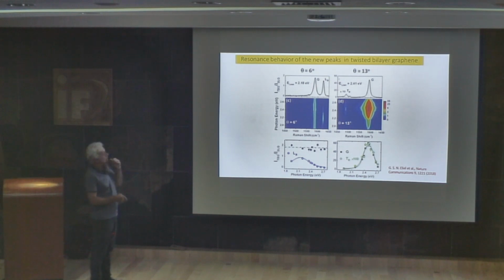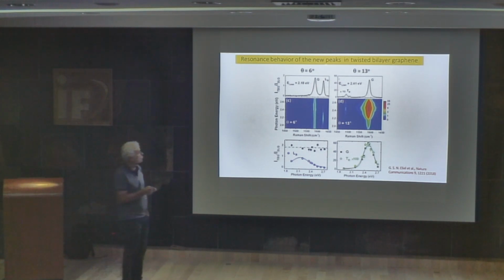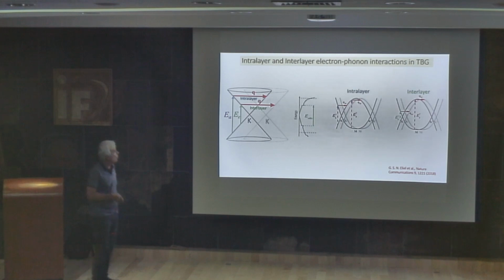Okay, then I don't have time to go into details, but what we could see are two different kinds of peaks that appear. One appears when the G band is not in resonance, and the second appears when the G band is in resonance. Then what we showed in this work is that we can have this double resonance process, as I showed you, this kind of process.